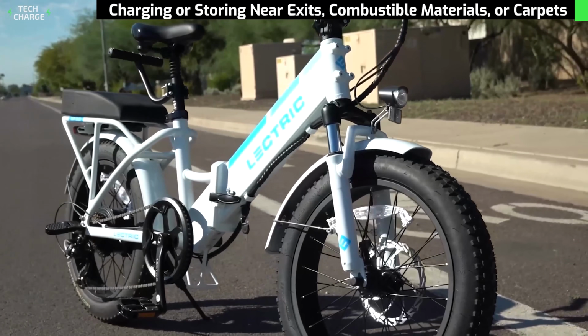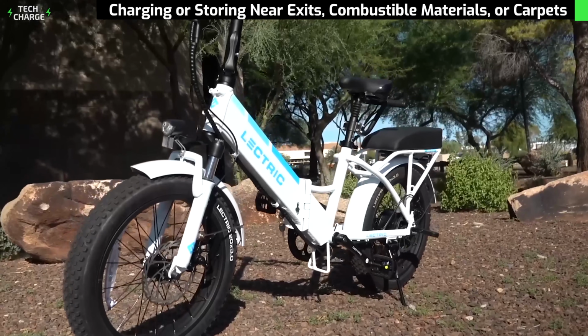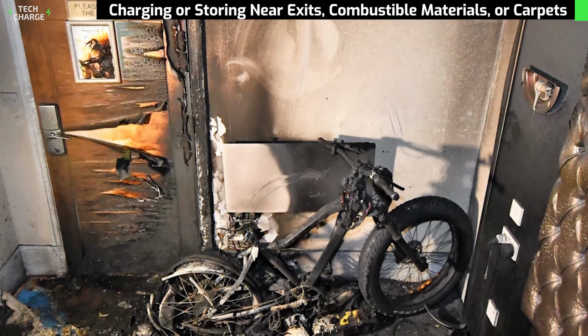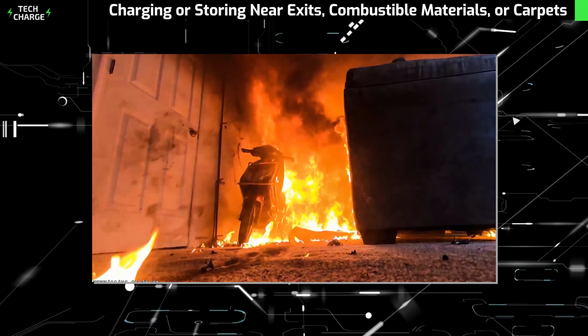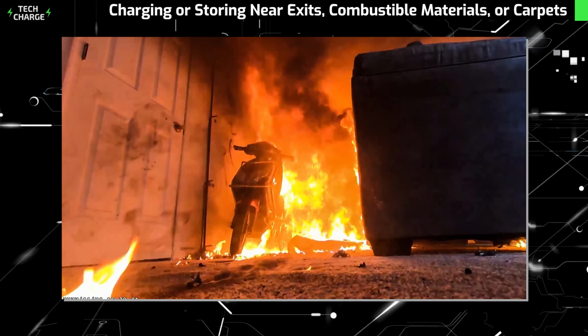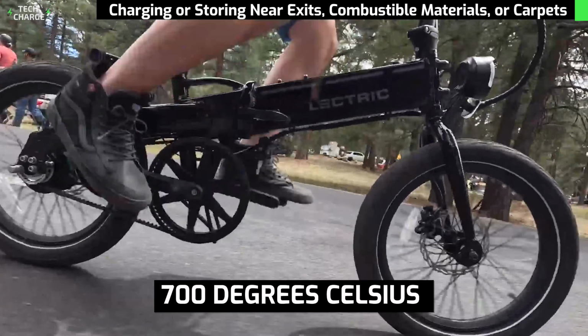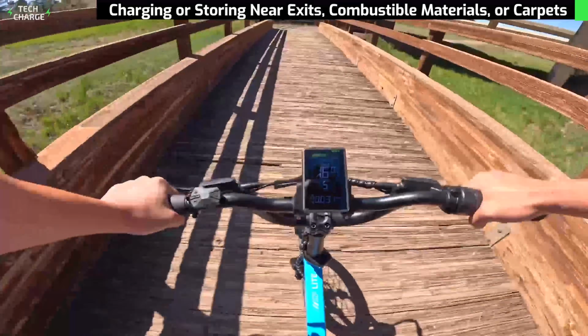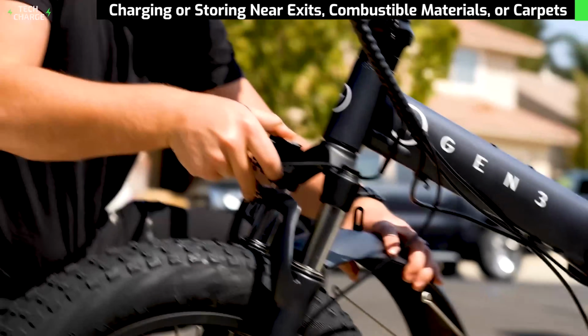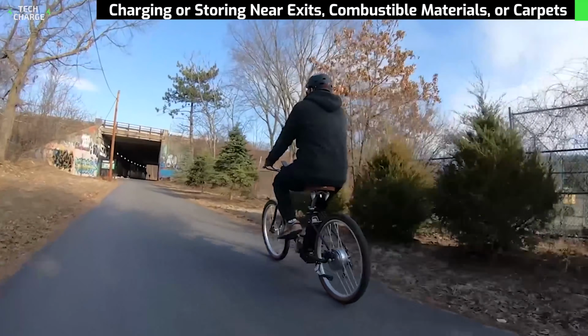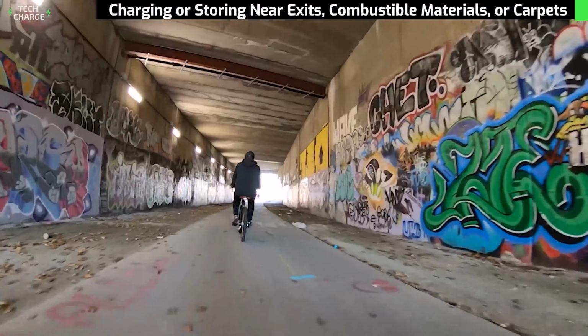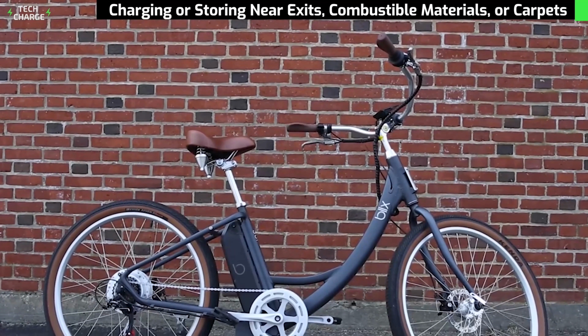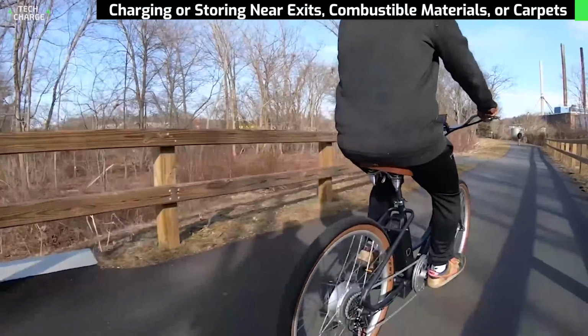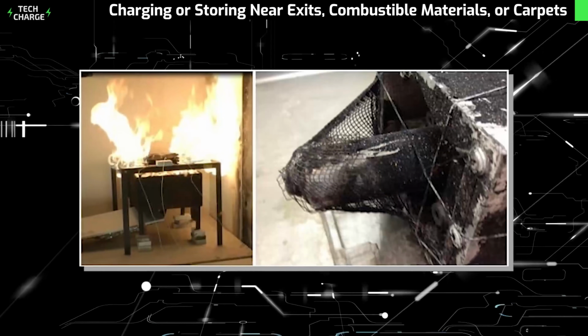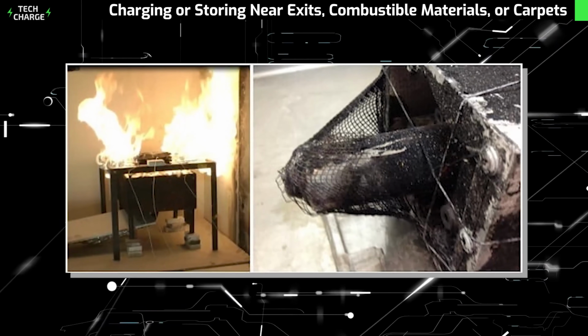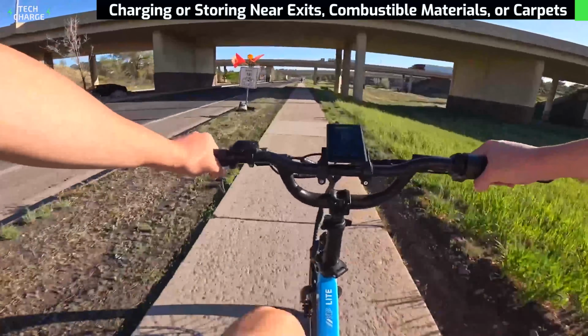The physics of lithium-ion fires explain why location is so critical. When thermal runaway occurs, the fire is extraordinarily intense and spreads with shocking speed. Temperatures can exceed 700 degrees Celsius within seconds. Storing or charging an e-bike near flammable materials like wood furniture, paper storage, curtains, or carpeting guarantees that a battery failure will instantly become a full structural fire. The released heat and flames will ignite secondary fuel sources immediately, creating a self-sustaining conflagration that overwhelms fire suppression efforts.